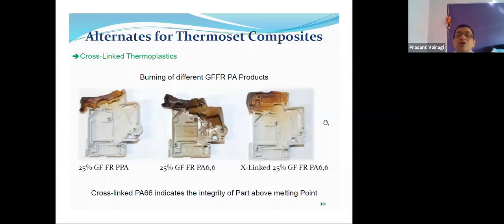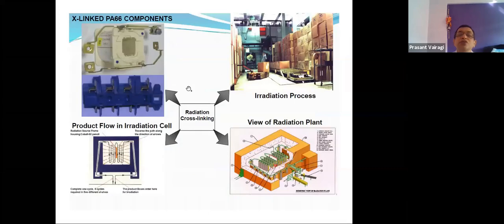And if you see here, the cross-linkable material has only given a white stain. Here also, with the glow wire, it is only a stain mark. You can't see any other effect as far as melt deformation is concerned. So this can be treated as an alternate to thermoset composite if you go about it in the right manner. It is basically for boosting the short-term high heat resistance while keeping the same injection molding process. That means all your thermoplastic molds will remain the same. You can take advantage of all the thermoplastic design features, which is not practically feasible with thermoset material.